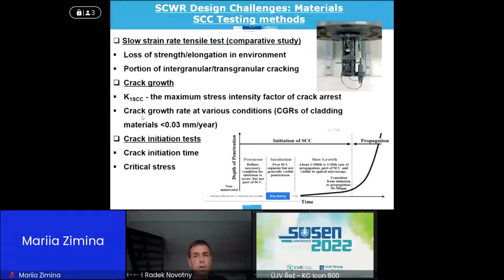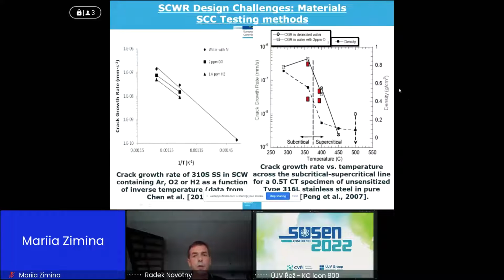And of course we need to focus on crack initiation tests, because initiation is a big part of the whole process. The propagation is only a smaller part. So we need to have a look at that and to follow from the precursor up to the growth of short cracks. There are only a few examples so far of fracture mechanics based crack growth rate tests.